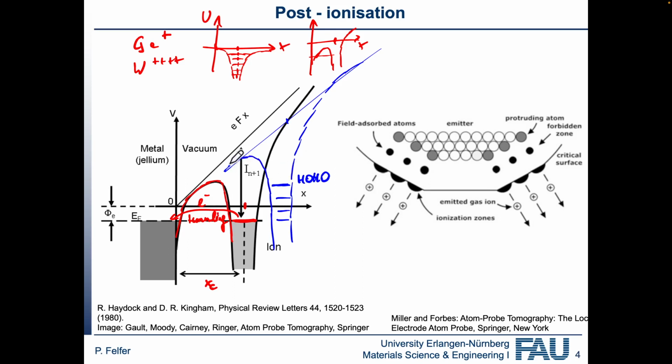But here, of course, the tunneling distance would already be quite a lot longer, but the energy incentive would be higher. And this is a trade-off. If you're too close, you cannot get ionization because the electrons would need to gain energy. And if you're too far away, the tunneling probability just becomes very low. And somewhere in between, we can have post-ionization.